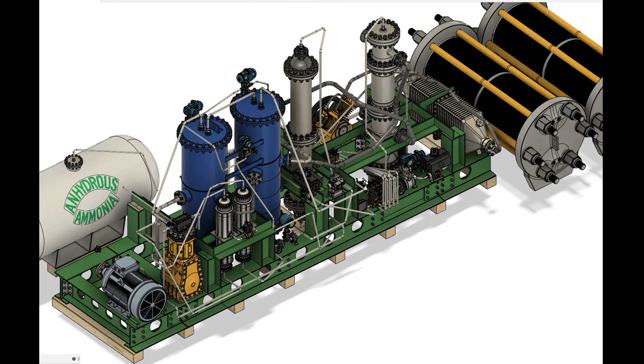Since we have covered the key requirements of synthesis gas compression that makes the Haber-Bosch process unique among chemical production methods, we will cover the topics of reaction kinetics as determined by scale, and its design implications. The kinetics of the actual reaction, of which the most important is the rate-limiting step of nitrogen dissociation, is not affected by the gross volume of the catalyst. It is, however, strongly affected by the pore size of the active catalyst and its packing density. The second variable is often mistaken for kinetics.